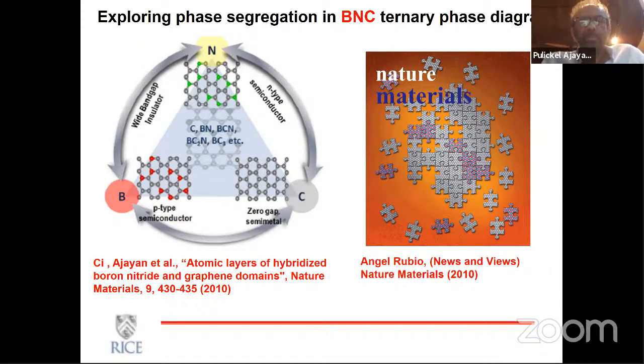We were specifically interested in looking at mixing the boron, nitrogen, and carbon and seeing how the phases remain as you change temperatures of growth and so on. And in general, what we find is that boron and nitrogen has a strong tendency to go together, and carbon with carbon separate. So if you make a growth with these different precursors to make a graphitized B, C, N system, you end up with what you're seeing on the right image, kind of a patchwork of domains. And depending on the conditions of growth, you can get nanocrystalline or microcrystalline domains of the completely segregated boron nitride and graphene.